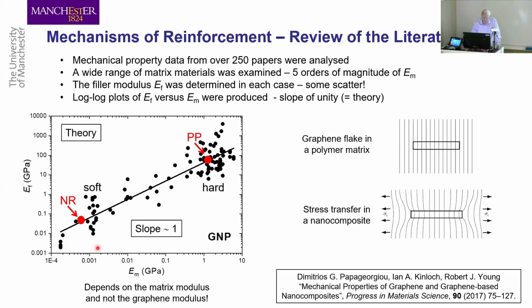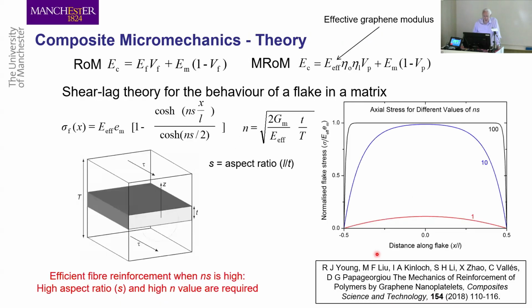This line had a slope of 1, which said that the stiffness of the graphene is proportional to the stiffness of the matrix. It wasn't 1,000 gigapascals, it just depended on the matrix, which is really odd. But when you go through the mechanics of everything, it actually fits in with shear lag theory and the transfer of stress to a reinforcement in a matrix. We've covered this in Progress in Materials Science, a whole series of papers on this. But essentially, you can analyze it using shear lag theory.